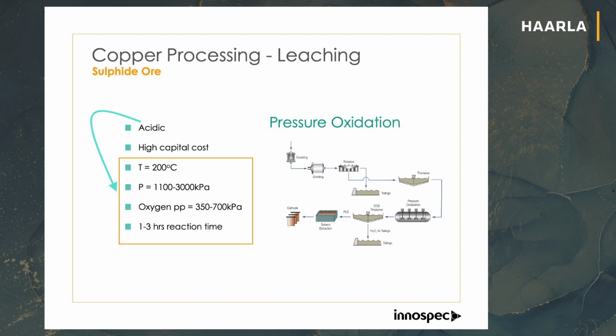So there's about 3 different types of process. One of the traditional ones is the pressure process, where you're taking the material from the flotation through the thickener cell and then into the pressure oxidation, where you're getting the copper out as a solution, which then goes through into the solvent extraction and through the electrowinning process. In both of these, you've got tailing processes that come out on two different parts of the process. This is obviously a capital intensive piece of equipment, and you can also do this in a bulk tank, where you've got the settling in there and doing it at atmospheric pressure.